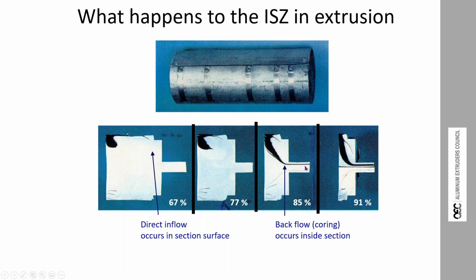So there's no way you're going to stop at this point and shear the butt off. Nobody's going to make you a butt shear which will shear a 4 or 5 inch butt very effectively, particularly in stronger alloys. But it's not yet reached the point at which I would call it coring, because this is really exaggerated because it's anodized up jet black. But you see here the type A inflow is getting stronger.